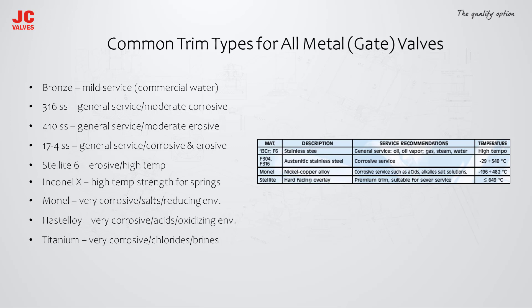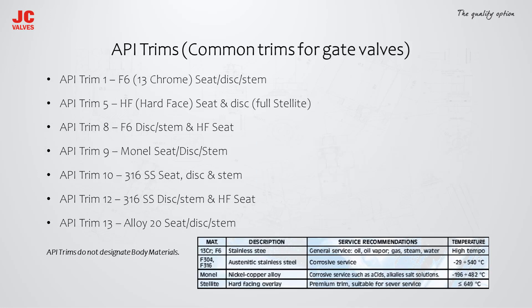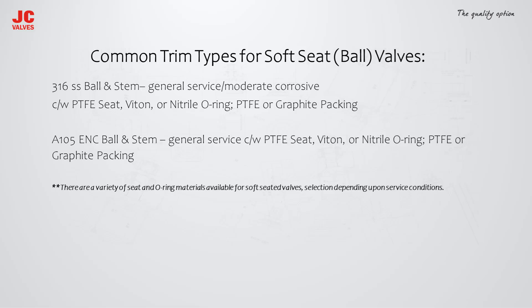Flow medium properties — chemical composition, pressure, temperature, flow rate, velocity, viscosity, erosion, and corrosion considerations — along with relative cost are important in selecting suitable trim materials. API has standardized trim materials by assigning a unique number to each set. The most common is API Trim Number 8: nominal trim is 410 with hard-faced; trim code F6 HFS; stem and other trim parts are 410 (13Cr, 200–275 BHN); disc or wedge surfaces are 410 (13Cr, 250 BHN minimum).